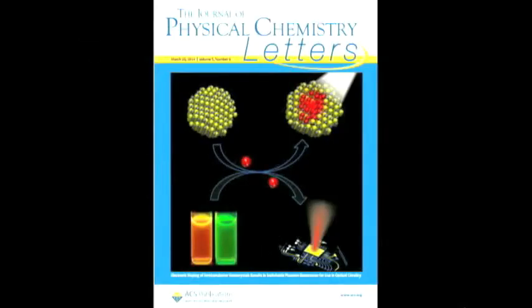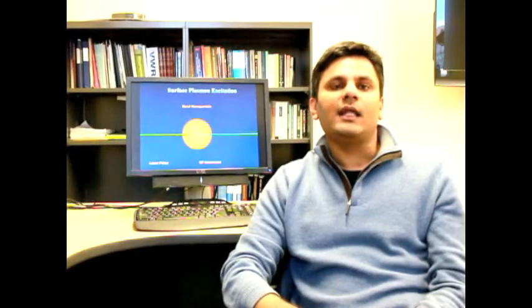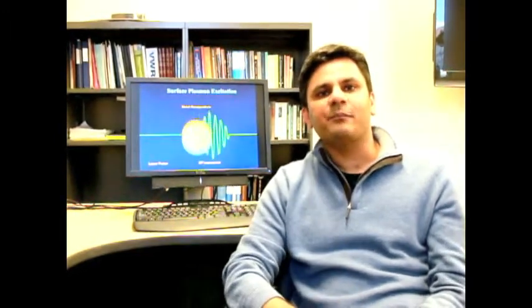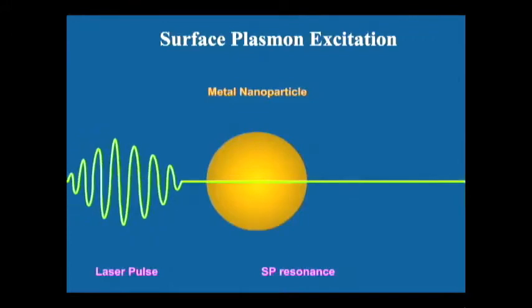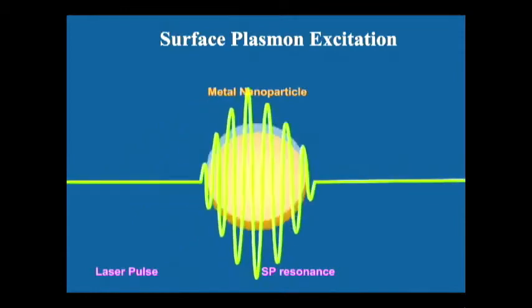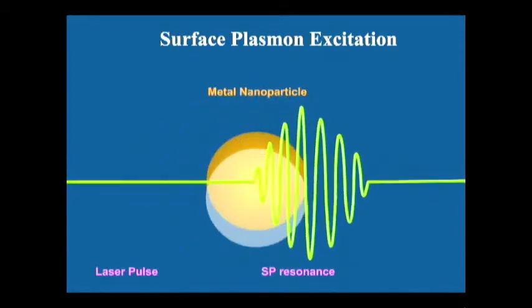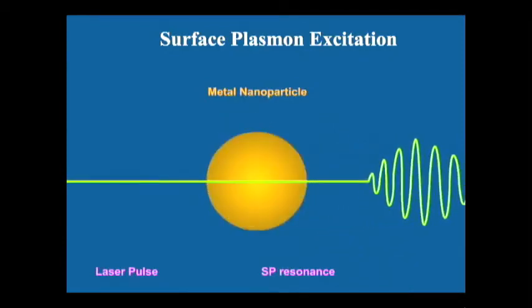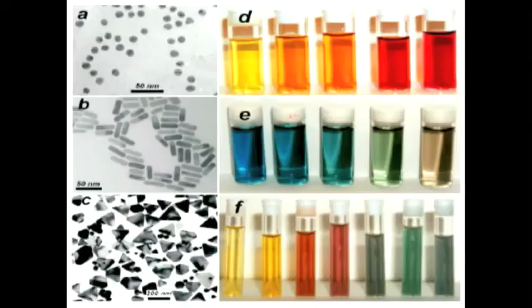This perspective article gives our view of an exciting new field that relates to the so-called plasmon resonances. So what are plasmon resonances? Essentially, if you take a nanoscale chunk of a metal, it has a whole bunch of free electrons, and these free electrons have a natural frequency or natural resonance at which they oscillate back and forth in response to visible frequencies of light — and that's what gives these metal nanoparticles their bright and brilliant colors. Essentially, a metal nanoparticle is like a tiny antenna.